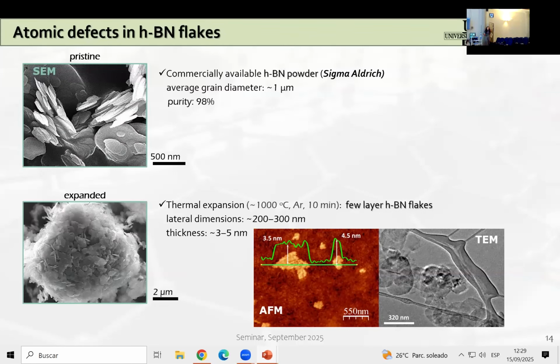Now, in order to produce quantum light emitters inside these grains, what we did is we thermally expanded them in argon atmosphere at around 1000 degrees Celsius for about 10 minutes. And this resulted in hexagonal boron nitride flakes, which are much thinner. So we are talking about a thickness of 3 to 5 nanometers and lateral dimensions of 200 to 300 nanometers, which we extracted from these AFM and TEM images here.